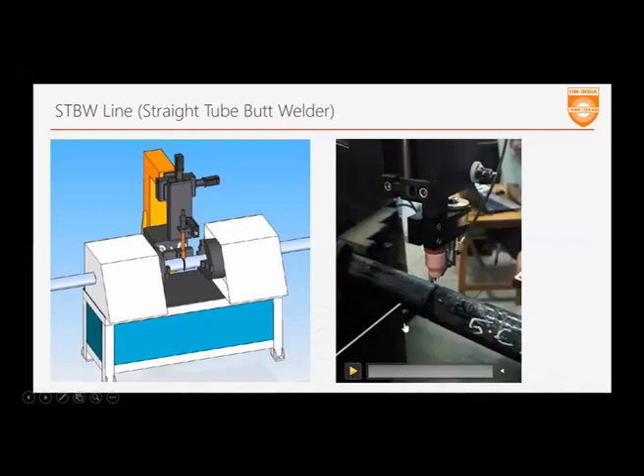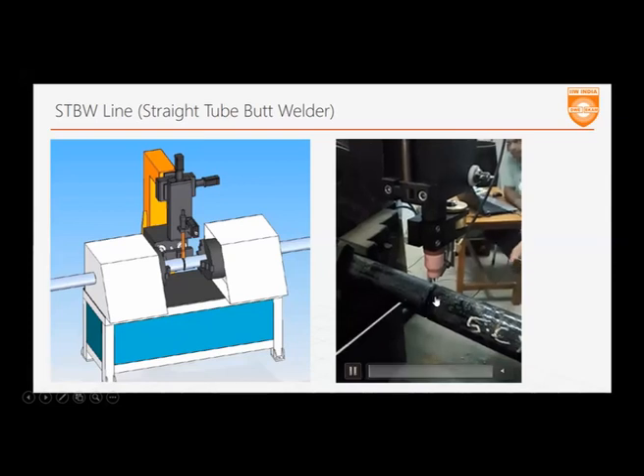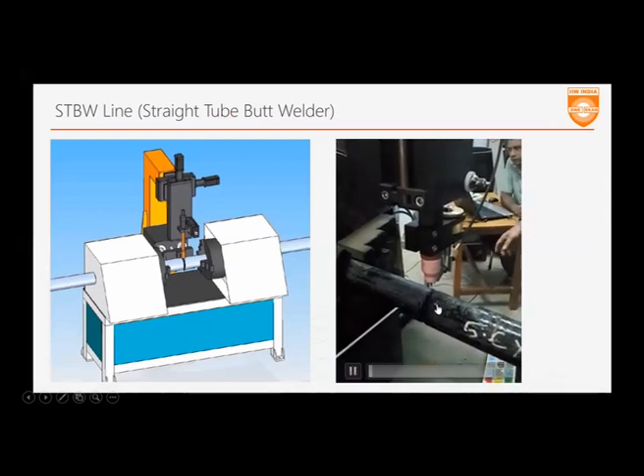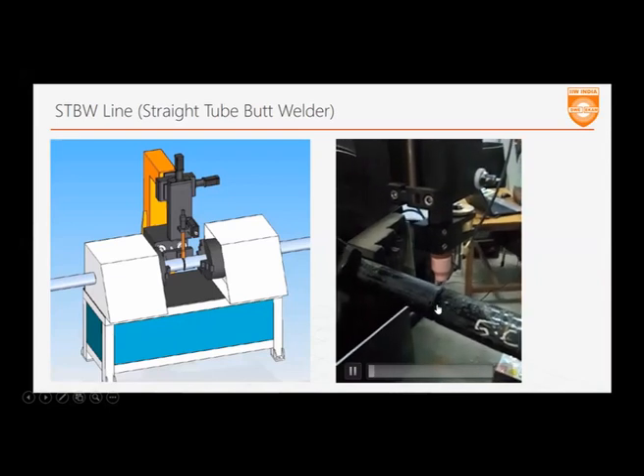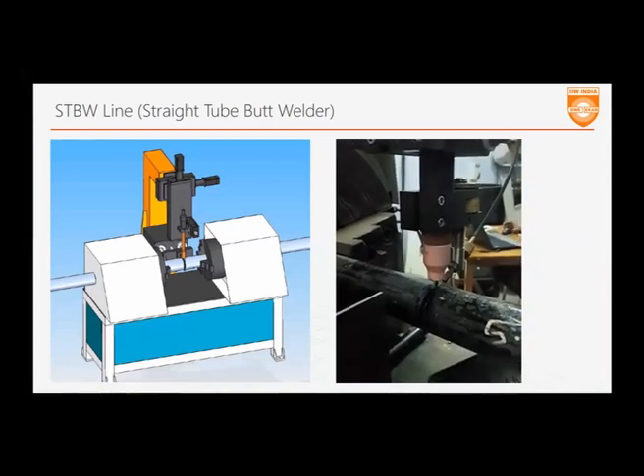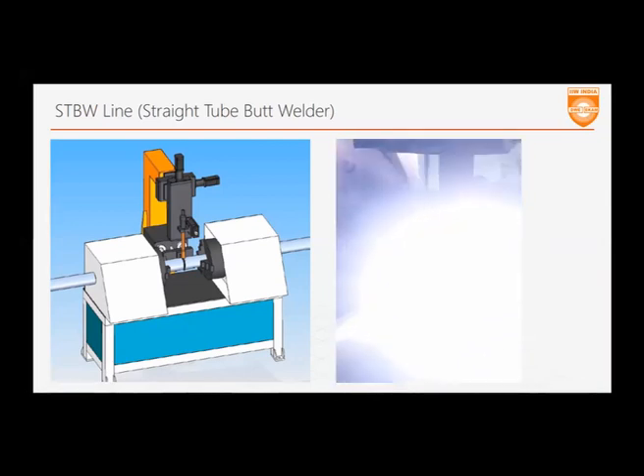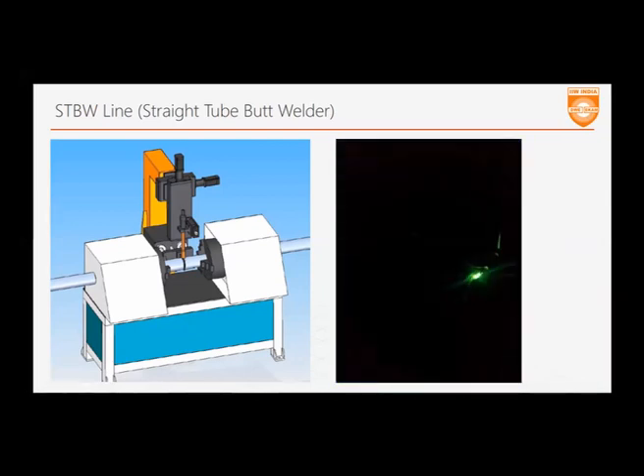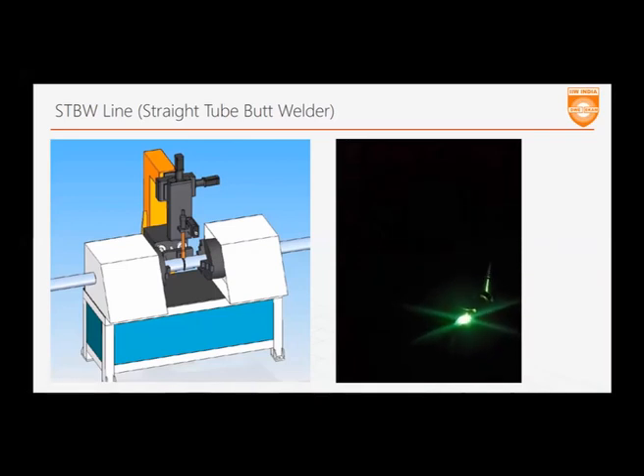So you see a touch retract happening here, wherein the torch is approaching the job. When it touches, the beauty of AVC is the feedback. When it touches the job, it tells you that it has reached the destination. It goes up by a fixed distance that you want to set and then starts the arcing. This will repeat itself every single time. You can have the start point at 3 millimeters, 4 millimeters, depending on the voltage you wanted.